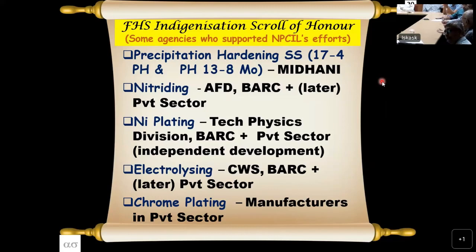They developed it de novo from the ASTM chemical compositions. Initially they found a lot of problems, along with DAE also. They were not meeting impact requirements. Then they found out the secret. The columbium plus tantalum control is required for getting the impact. Now it is proprietary information for them. I too don't know what that combination is, but it is required. So they have done it. Since about Narora time, all our requirements are being met by Midhani. Midhani has done a very, very terrific job.